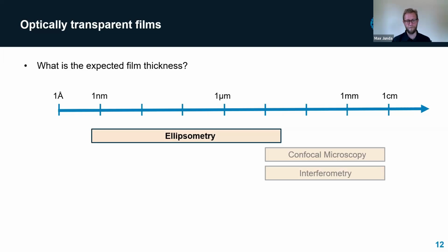Ellipsometry can be used in a variety of cases. It can also, quick plug, be used to measure films that aren't optically transparent. However, the key thing is in cases where you want to measure the thickness of films that are present, it does require optical transparency. The light needs to be able to make it into the film and get back out. So you can see really quick just on this schematic here that ellipsometry is able to access film thickness over a really wide range. It spans basically angstrom, so almost atomic layer, up to tens of microns in a practical sense. So we'll go to the next slide.